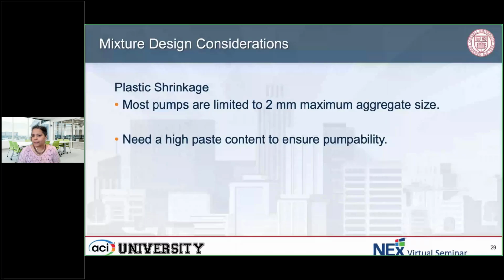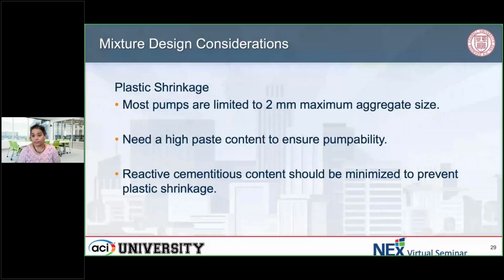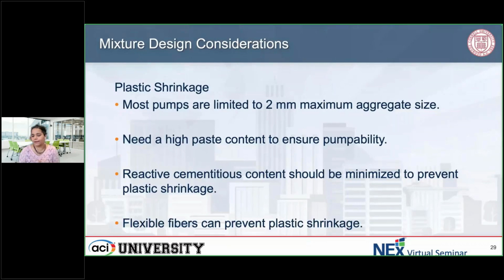So in that scenario, you need to minimize the amount of cementitious content that you have. You can still have a large powder content similar to what you have with UHPC, but you need to reduce your reactive content so you can minimize your shrinkage. You can also use flexible plastic fibers or glass fibers. As long as they're flexible and thin and the pump won't get damaged, then you should be fine and you can use them for plastic shrinkage.